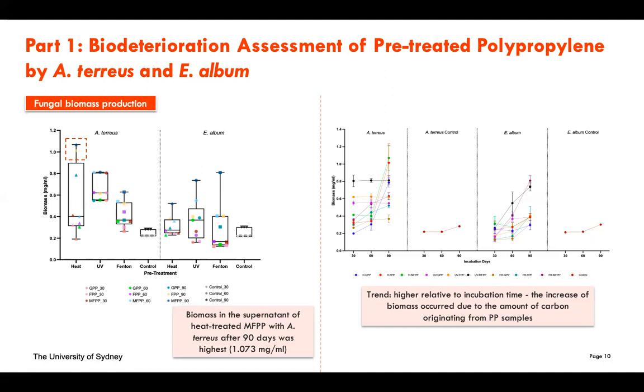So we want the fungi to be able to grow throughout 30, 60, and 90 days. So we indicated the growth based on the fungal biomass. When we weigh the biomass, there is an increment in terms of 30, 60, and 90 days. So we know that some of the fungi are able to grow and feed on the polymer that we feed them. Okay, so in other words, the higher mass increase after 90 days in the presence of polypropylene could be attributed to the use of the polypropylene itself as the nutrient source. So they can feed on this polypropylene.